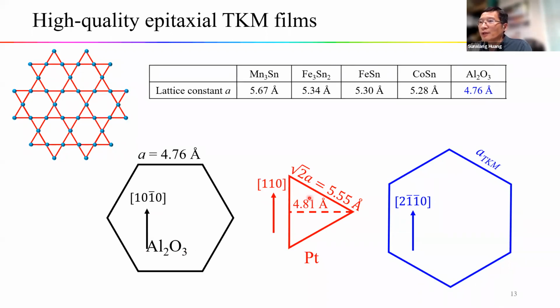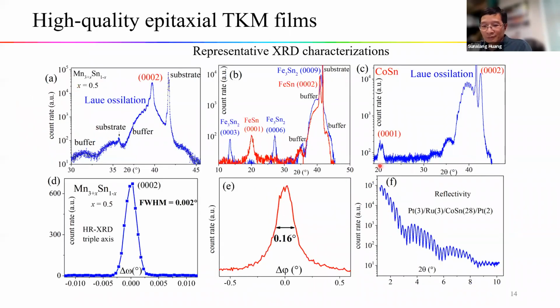If we look at this value, this is 4.81 and this is 4.76. The difference is less than 1%. And now if we look at the lattice length, it's about 5.55 angstroms, which is about a 2% difference with the manganese-tin. Furthermore,